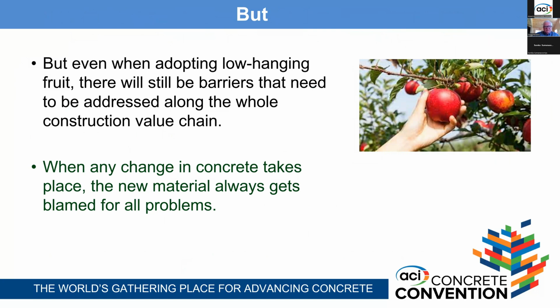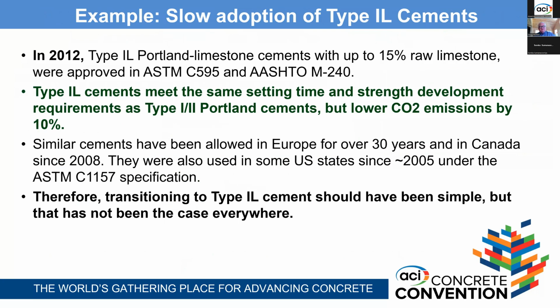But even when we're trying to deal with these low-hanging fruits, there will still be barriers that need to be addressed along the construction value chain. When a change in concrete comes along, the new materials always get blamed for any problem that occurs in concrete. And problems occur every day of the week in various applications. One example is the slow adoption of IL cements, which is under C595. They were approved in 2012 in the United States through ASTM and AASHTO, even earlier in Canada. They meet all the same setting time and strength development requirements as a type I/II Portland cement, but have lower CO2 emissions by 10%. They've been used in Europe for almost 40 years now, and in some US states for almost 20 years. Colorado and Utah are 2 examples, and they were used before IL was available under the 1157 performance specification. So it's been used in interstate pavements and other applications since 2005.